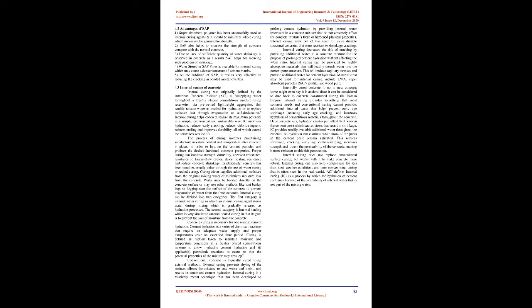The results of this study indicate that when internal curing is used, the overall water absorption and electrical conductivity is reduced. This is shown to be due to the increased degree of hydration and a depercolation of the interfacial zones around the aggregate. As a result, mixtures with internal curing may have a W/C of 0.30 but exhibit the performance of a concrete with a lower W/C, for example 0.23.